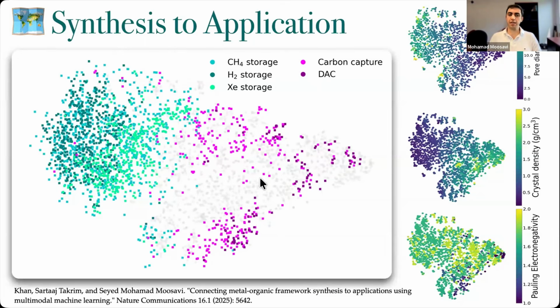The interesting thing is if you color code this map with, for example, crystal density or pore diameter, you see that materials with very high density are all clustered here, low density are here. These are the ones that are very promising for methane storage, hydrogen storage, xenon storage. So essentially the model learned something that was not the input of the model itself. We inputted just PXRD and precursors, but it organized this information in a meaningful way that has information about, for example, crystal density that is important for different applications. So now we can use this model to suggest different applications for a newly made material simply by inputting the PXRD and precursors of the material.